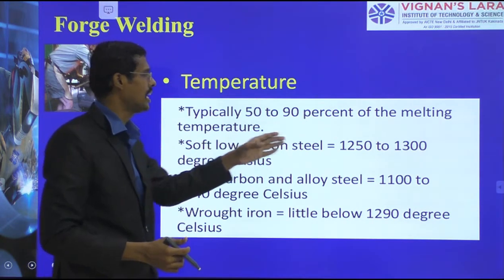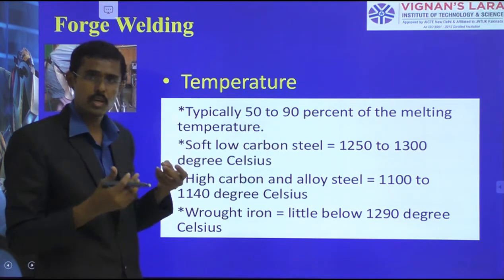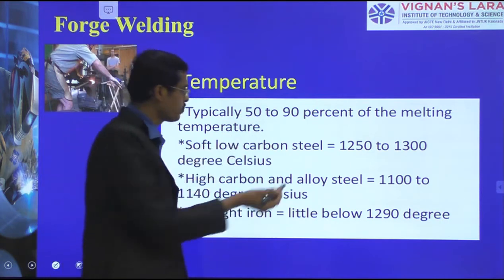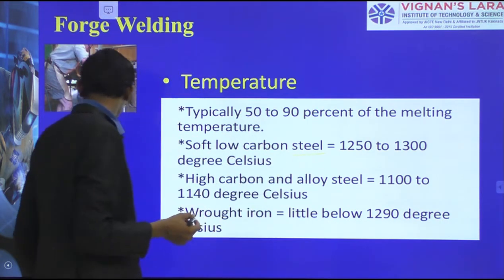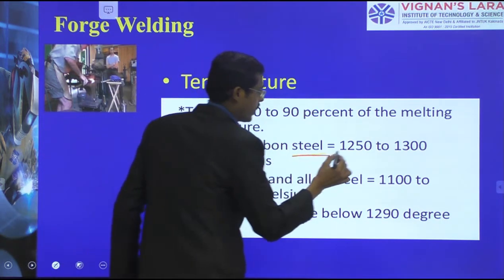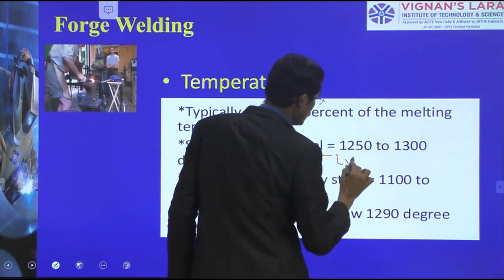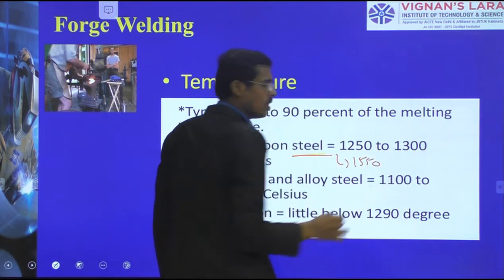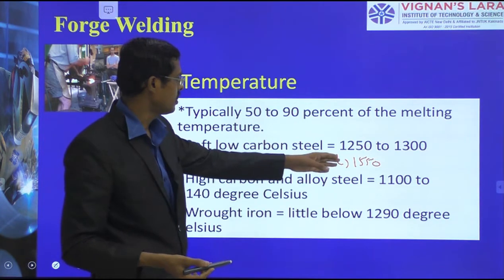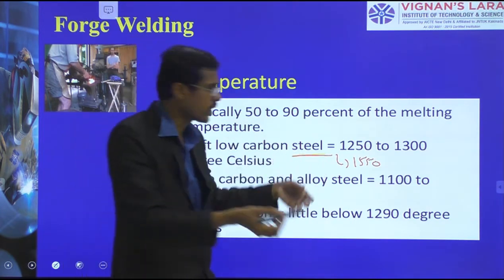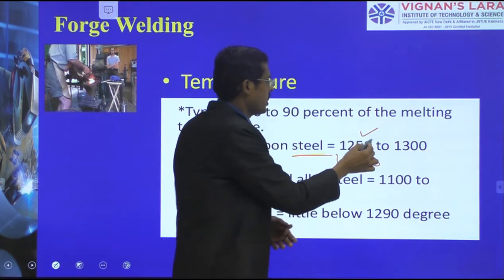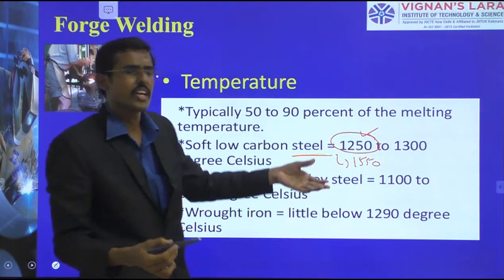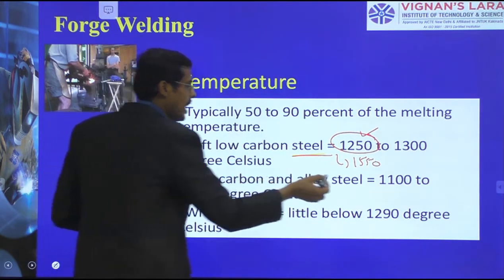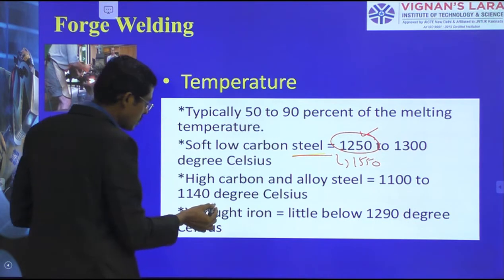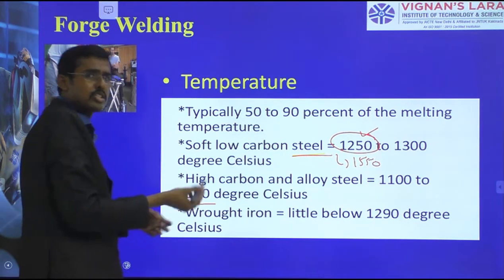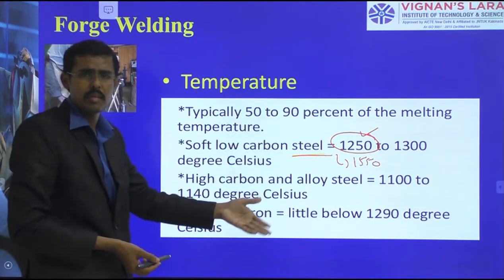The 10 to 20% differs depending upon the solidus temperature. For soft low carbon steel we are able to do this process because it still has a melting point of around how much? It is 1550 or 1500. So in this red hot condition we are working at around 1250 degrees centigrade, so 80 to 90%. High carbon alloy steel is around 1100 to 1150. Therefore, this depends upon the alloy system and the material.